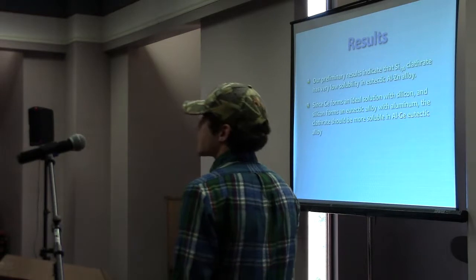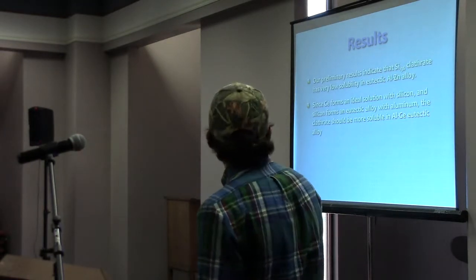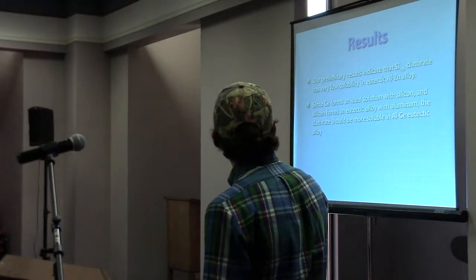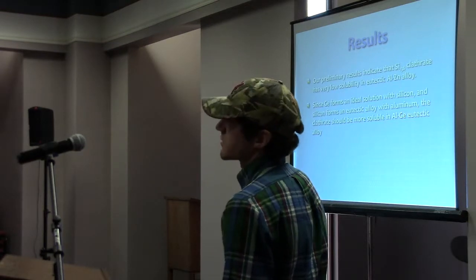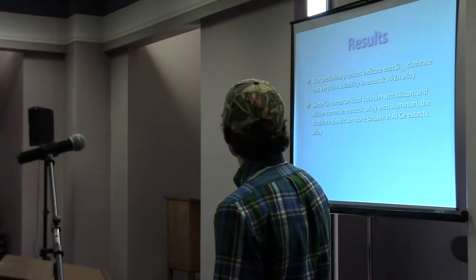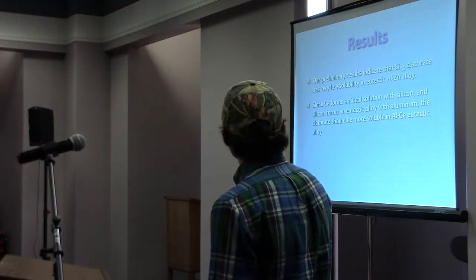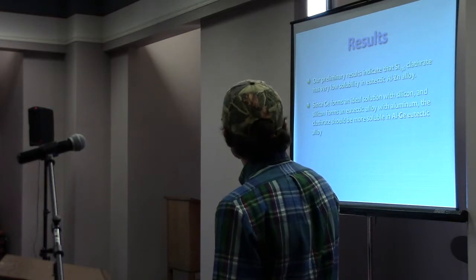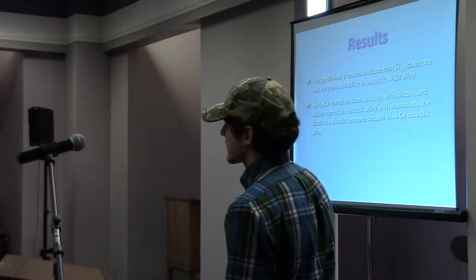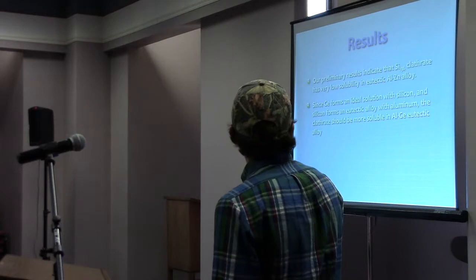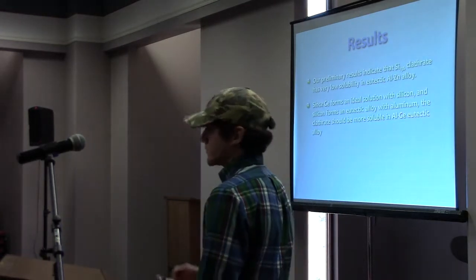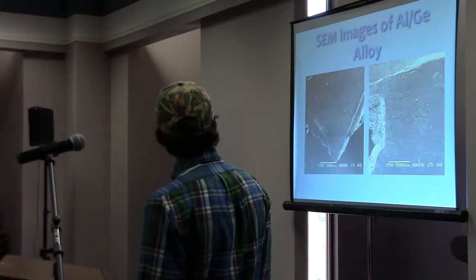Our preliminary results indicated that the aluminum-zinc alloy was not suitable for this case because the clathrate had very low solubility, and it actually, in fact, did not wet and was not miscible. But since germanium forms an ideal solution with silicon, and silicon forms a eutectic alloy with aluminum, the clathrate should be more soluble in aluminum-germanium eutectic alloys.